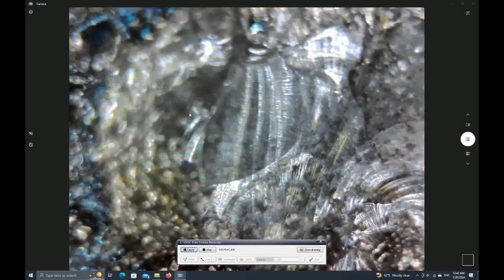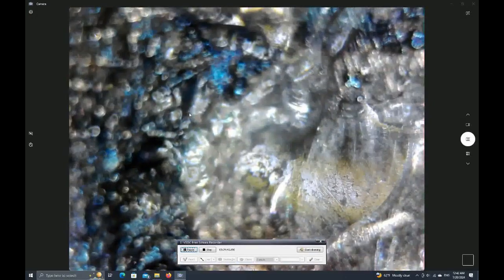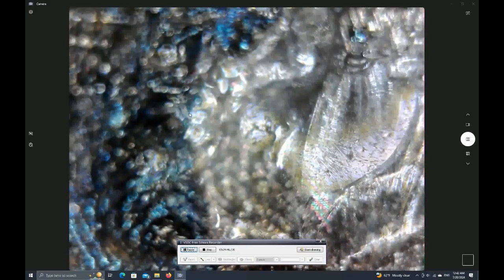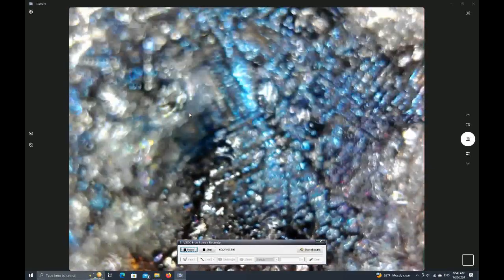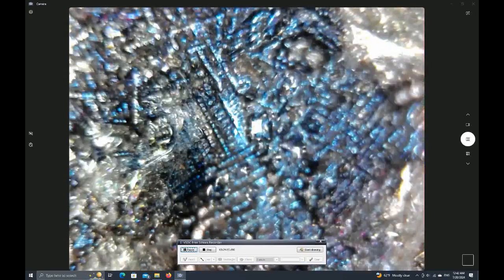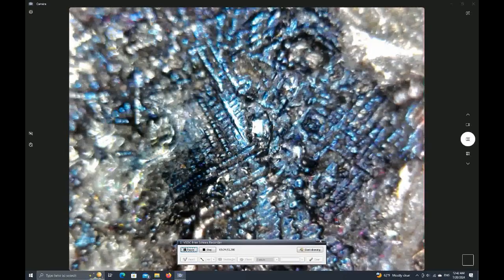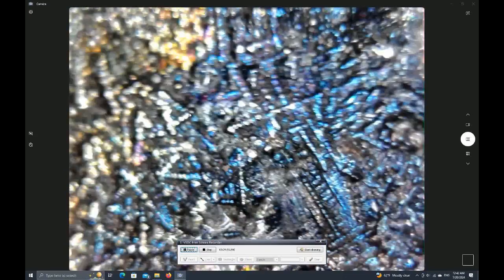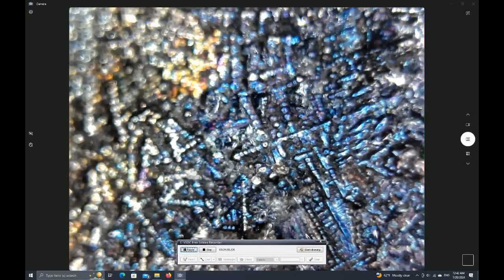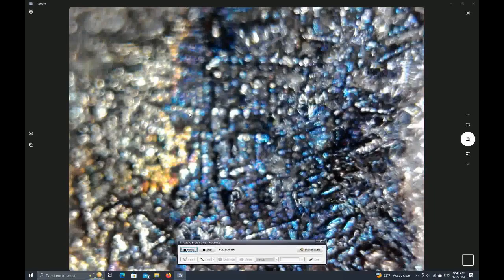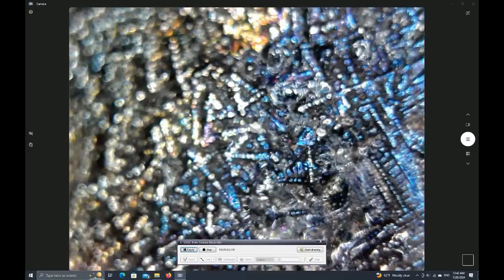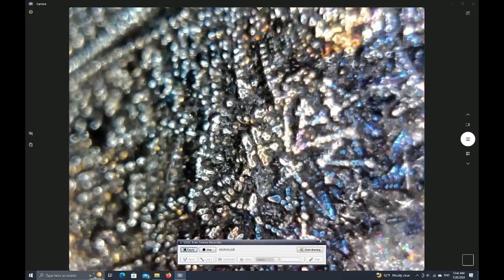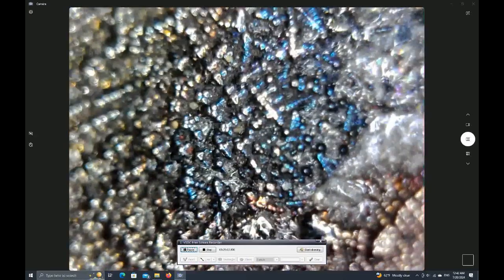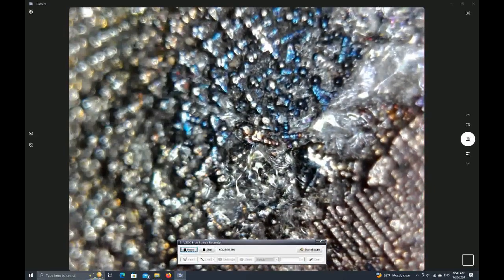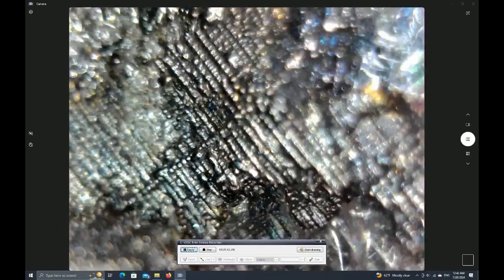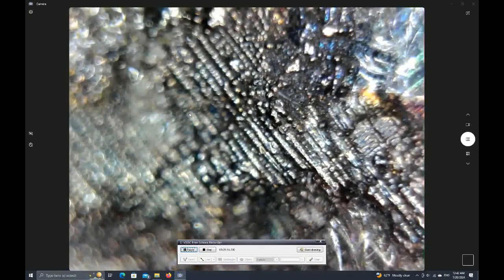What you're seeing here is glass that I can't chip out. It's in like these little craters that are just all over the surface of this ingot. I still have not figured out why I get these craters, and therefore I still have not figured out how to not get craters. I've always had them. I don't know if it's something inherent to using an induction forge versus using a coke forge or a forced air propane forge for crucible steel. I'm not going to find out until I build a forced air propane forge for this campaign.